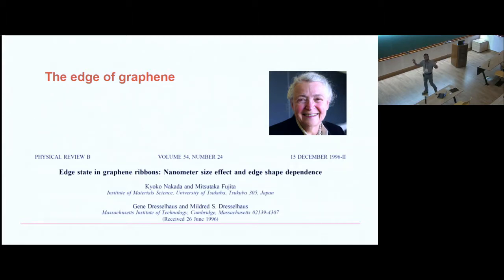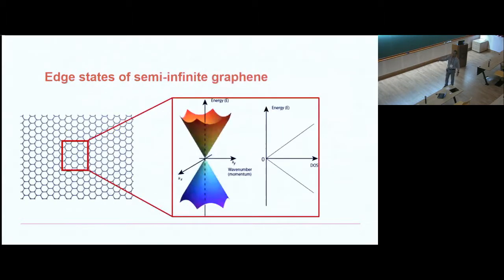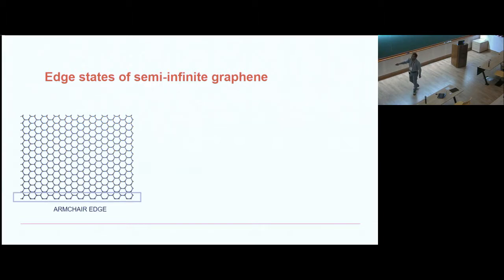Now, there is no topology there. Okay? So the first part has nothing to do with topology as such. The second part will have a significant component of it. All right, so if you have a graphene system, the bulk of the system has a beautiful linear band structure. We all know about it, and the density of states varies linearly. And you have zero density of states at the K point, and then the density of states increases as you go higher in energy. However, if you take a semi-infinite graphene, a very large system, there are two types of edges. One is the armchair edge, the other is the zigzag edge.